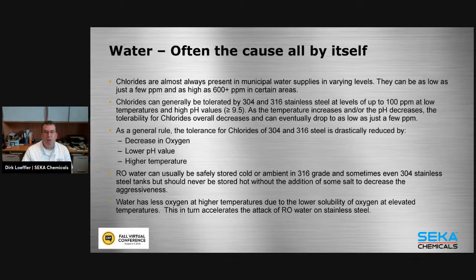Just to talk about that, water can often be the cause all by itself. Water can carry, depending on where you're located, a lot of chlorides in it. It can be iron, there can be a bunch of things. Keep in mind too, even if you do a carbon filtration of your water, it will break down the free chlorine in your water, but it will not take out the chlorides. Chlorine breaks down into chlorides, which is an elemental ion, and it will remain in the water. And the tolerance for chlorides of 304 and 316 is reduced by a decrease in oxygen. So if you have a CO2 environment like in your tanks, lower pH values, acid CIPs, and high temperatures, brewhouse, hot liquor tank, etc., etc.